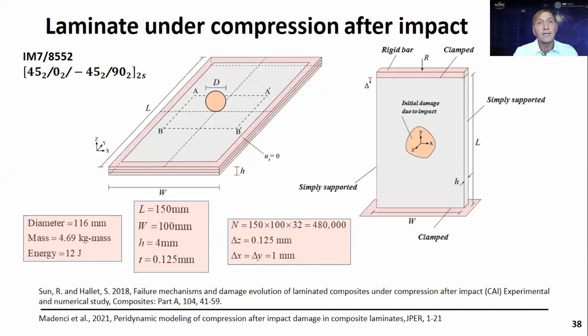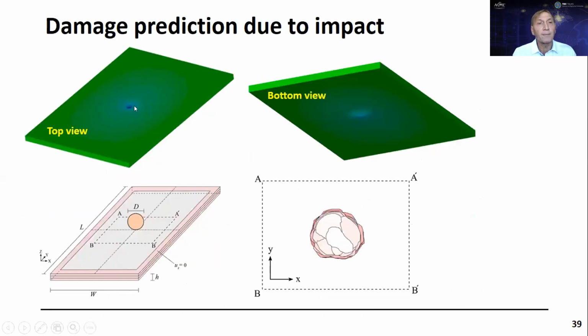And next I have the laminate under compression after impact. So we took the experimental study by Sun and Hallett, and we simulated it using peridynamics. The material is quasi-isotropic, IM7/8552. This is first subjected to impact, and then we took this impacted specimen or the model and applied a compression under these boundary conditions here. So the damage prediction, this is the top view, this is the bottom view, and this is the superposition of all the damage that you have.